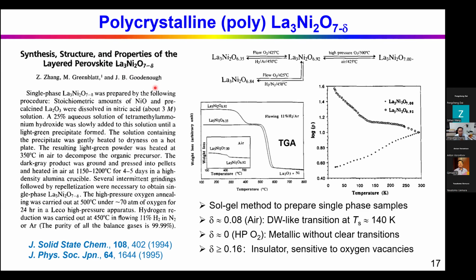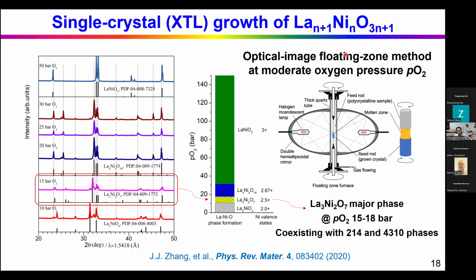In this paper they described in great detail how to prepare these samples. They used TGA measurement to confirm the oxygen content. If you sinter the sample in air, it has slight oxygen deficiency, with delta about 0.08. In the resistivity, it shows a density-wave-like transition around 140 Kelvin. But if you treat the sample under high oxygen pressure, the oxygen vacancies can be removed, and the sample tends to become metallic without clear transitions. If you create more oxygen vacancies, it becomes an insulator. So the transport property of this sample is very sensitive to the oxygen content, according to the earlier papers.